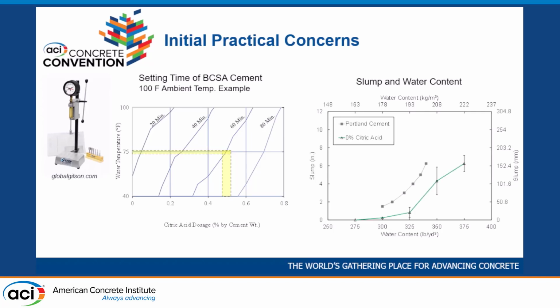So we did this kind of testing for BCSA cement. We find that for 0% citric acid, so no retarder, slumps are very low compared to Portland cement. Partly this is because with no citric acid, the slump retention really isn't good. It starts to set up really quickly. It's interesting, if we add citric acid, it makes the mix a lot more fluid, so we get a big increase in slumps.